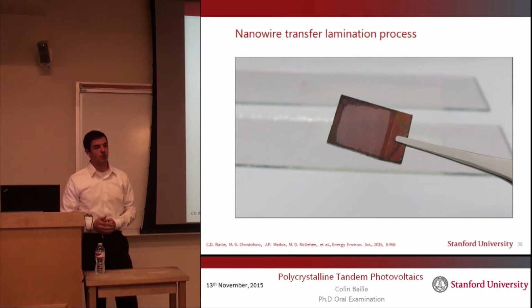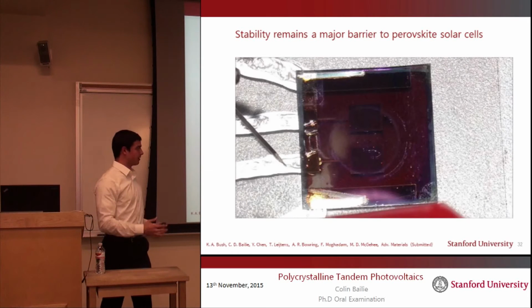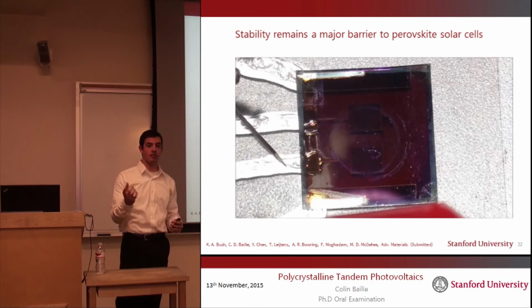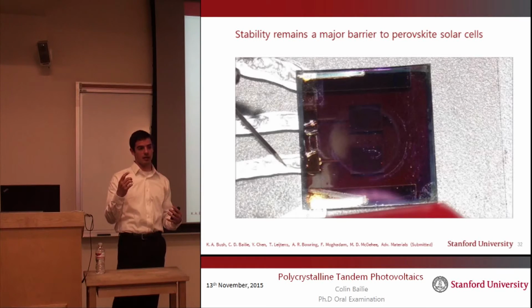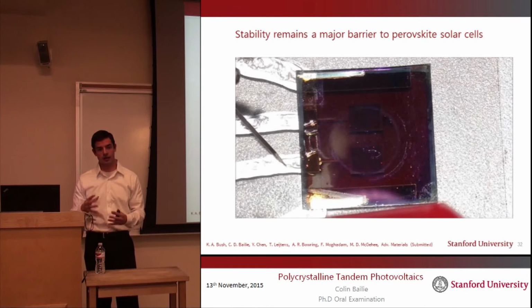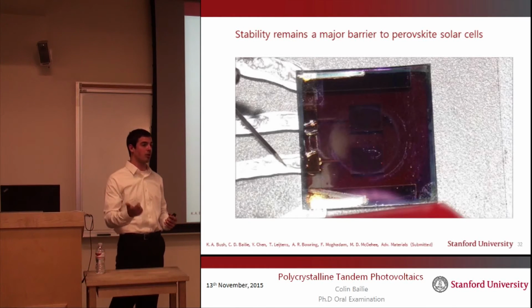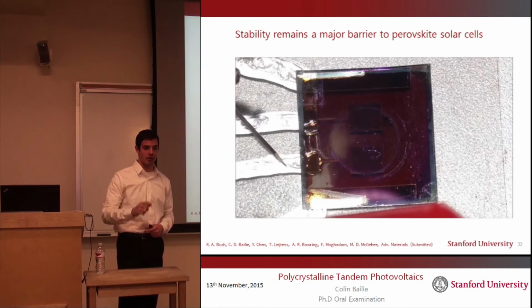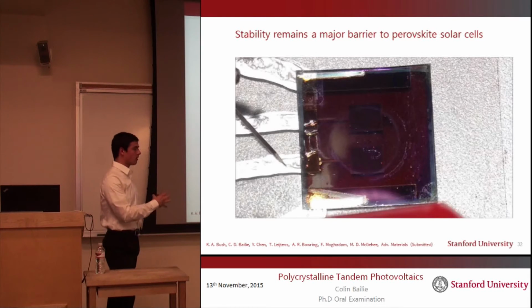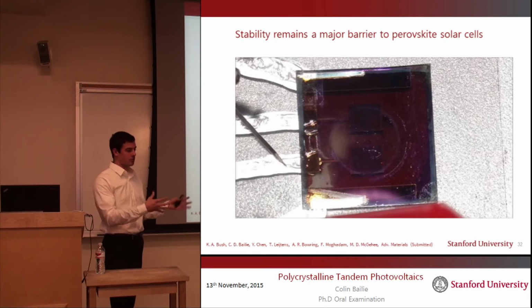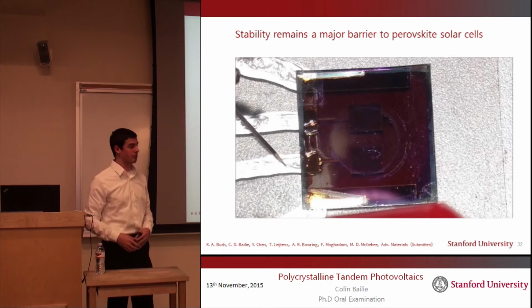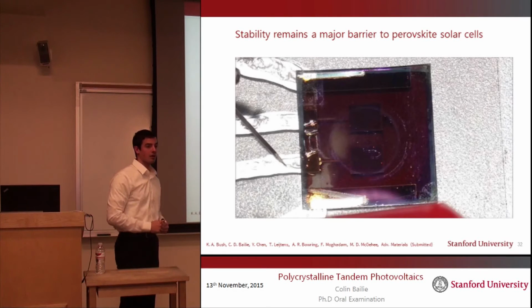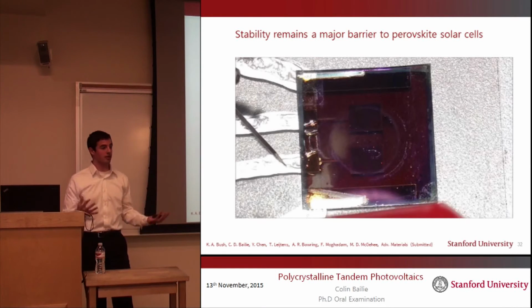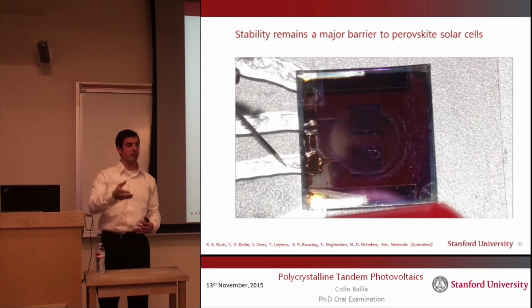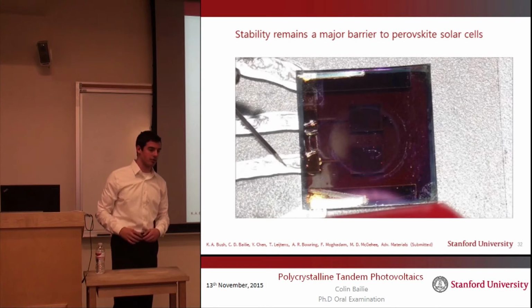But what we didn't do was stabilize the perovskite cell itself. Now, because this silver nanowire electrode was a mesh, that means there were a lot of holes between where there was actually metal. And where there are holes, all of the degradation mechanisms I mentioned before still prove true. So the organic can still evaporate through the holes in the metal, and the moisture from the air can still get in and degrade the perovskite.